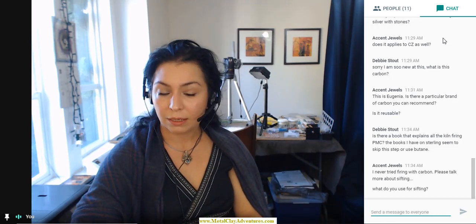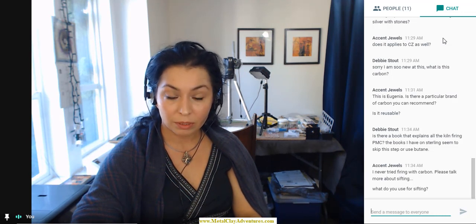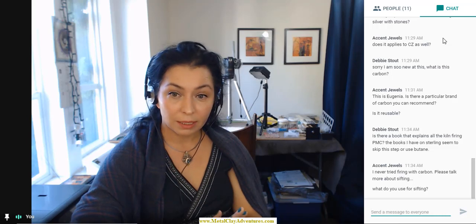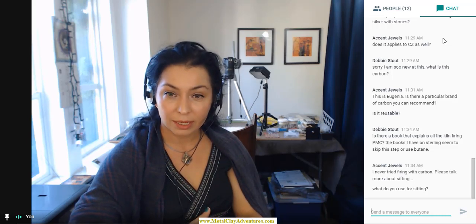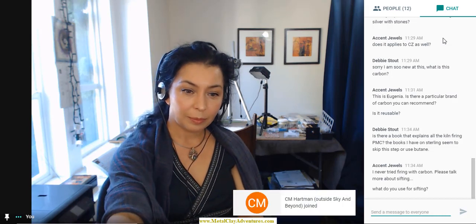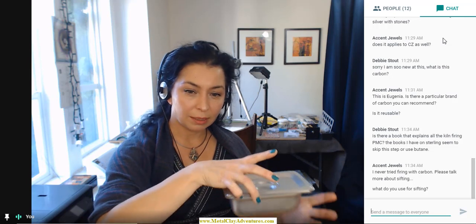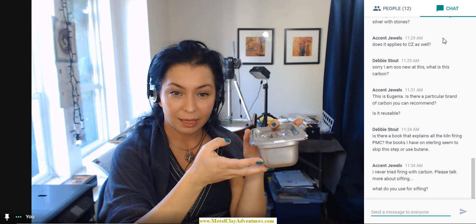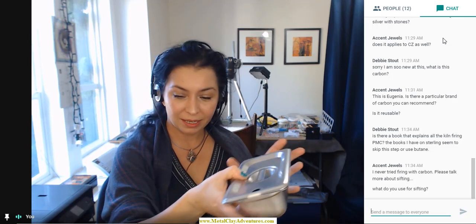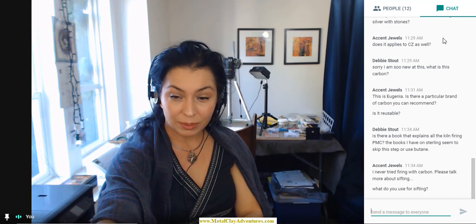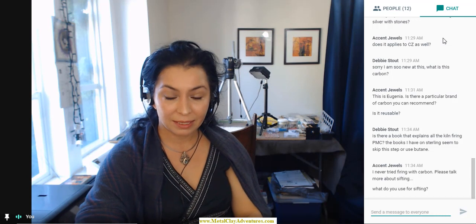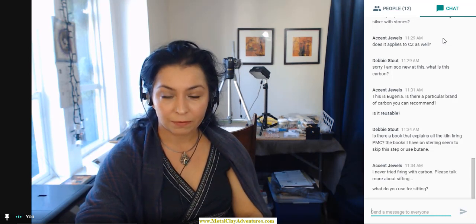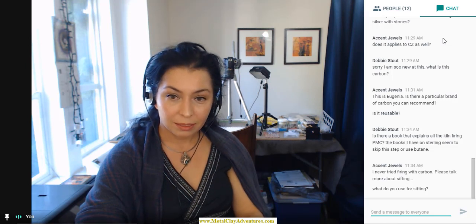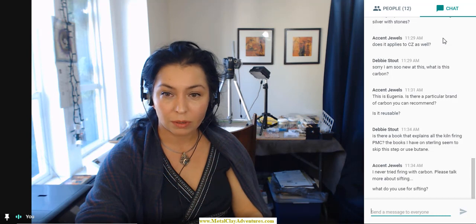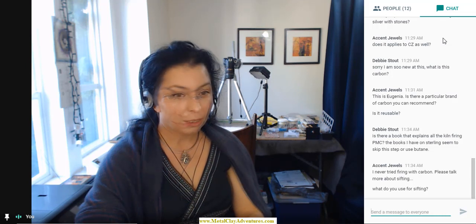Talking about firing alloys and base metals, we are talking about carbon firing. And we learned that the best carbon is the coconut activated one, and the best containers to use are the stainless steel ones. If you fire base metals every day for 1 year in one of these containers, it will disintegrate. We learned that we need to clean the carbon after each firing by sieving it. And when firing base metals or alloys, we need to test fire a strip every time we are putting a piece in the kiln.